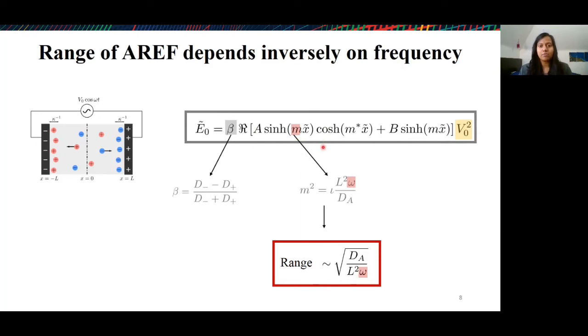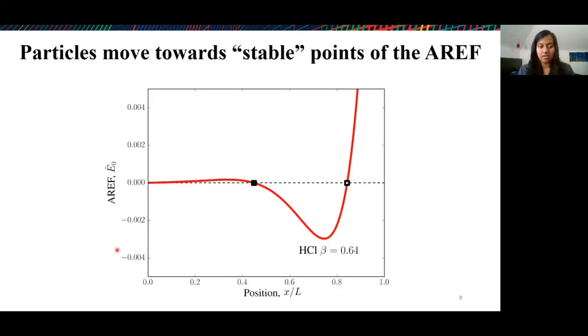So now we want to think of what particle motion actually looks like in these systems. So let's take a look at a plot of the electric field on the y-axis with the position on the x-axis. And this plot is particularly for hydrogen chloride. So here beta, the asymmetry parameter, is around 0.6. The electric field is non-monotonic. And so it becomes positive and then negative and then positive again and goes through 0 multiple times.